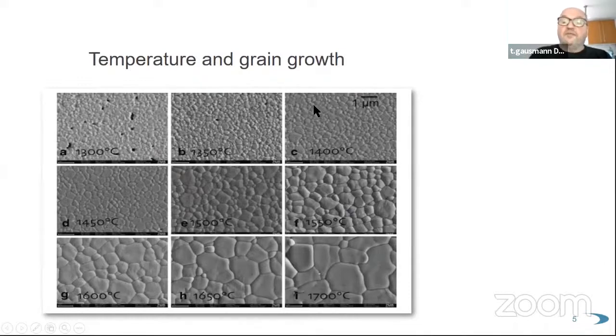But with these lots of grain borders, you have a lot of scattering of light. So this will be very opaque. 1400 degrees, barely strong enough, but a very opaque material. Then you've got the next temperature, depending on the material you're using, because I know other people like Amann are using 1450 as their general sintering temperature. They've got a different composition in the grain, but in general, this is the table like we have.